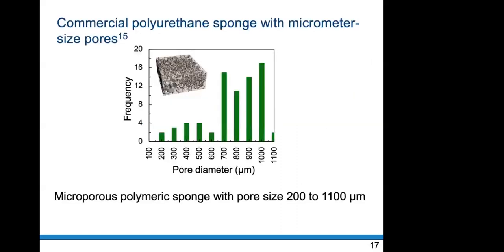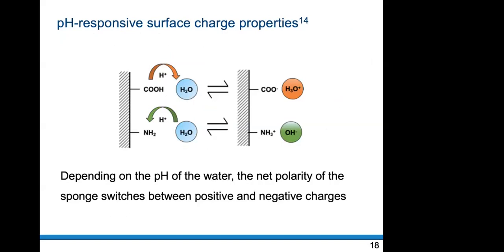So what we have done here is we have taken a commercial polyurethane sponge, which has a large pore size and a bimodal pore size distribution. The specialty about this specific sponge is it has both carboxyl and amine groups. The advantage of these groups is that in response to the pH of the surrounding water, it can switch between positive and negative charges. This charge property would be beneficial in catching the bacteria from the surrounding water via electrostatic attraction, or repelling them from attaching to the surface.